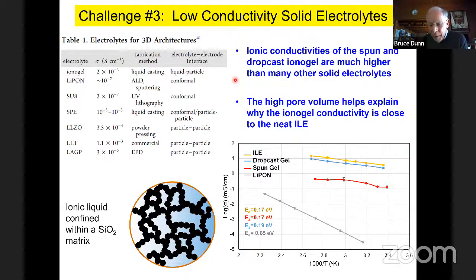So what we've been working on are what are known as ionogels. Ionogels are materials where you combine the sol-gel process with an ionic liquid. So instead of using a common solvent like ethanol that evaporates, you use an ionic liquid. It doesn't evaporate, but it does transport lithium ions extremely well. It has a wide electrochemical window, and it has very good conductivity. And as you can see here, the conductivity of the ionic liquid electrolyte, this one or even this one, is orders and orders of magnitude higher than LiPON. So we now had a very good conductive system.